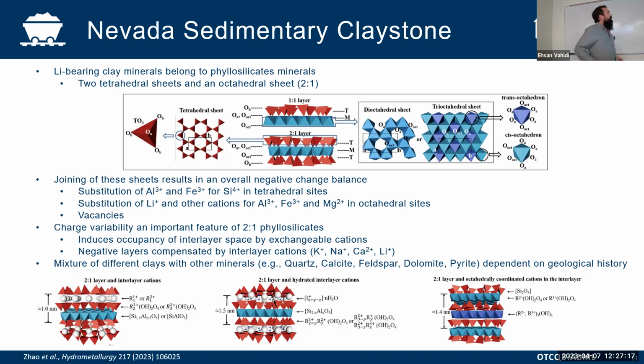Now, this charge variability is a very important feature because it induces occupancy of layer spacing for exchangeable sites of cations. So this is an important feature of these clay materials that we can utilize for extraction. These negative layers are compensated by positive cations, which can be sodium, potassium, calcium, or lithium. They can either be in ion exchangeable sites or within the actual structure of the material.